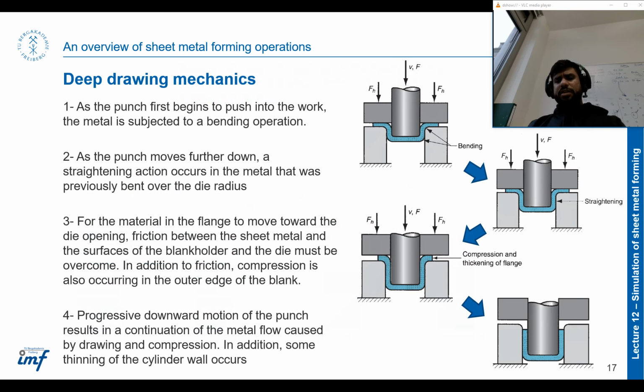The details of the process are given here, where, for example, we see that when the punch first begins to push the work, the material is subjected to a bending operation. So we see here that bending is taking place here and bending is taking place here. And then as the punch moves further down, in case of this figure, a straightening action occurs. So there is a bend first and then it becomes straight here, that was previously bent over the die radius. So this causes the strain hardening effect in the material because we are bending it first and then straightening it later. And that makes the wall of the drawn part relatively stronger than the lip or the bottom of the part.